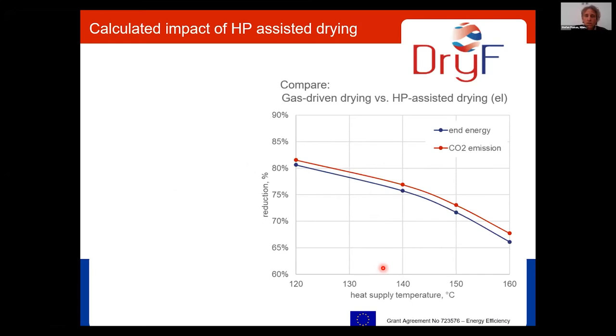When we look at the environmental impact, we see that the benefit drops the higher the sink temperatures are. But when you look at 120 degrees, where we operated in Uttendorf, calculations show that we can reduce energy consumption and CO2 emission by about 80% compared to a gas-driven drying process.